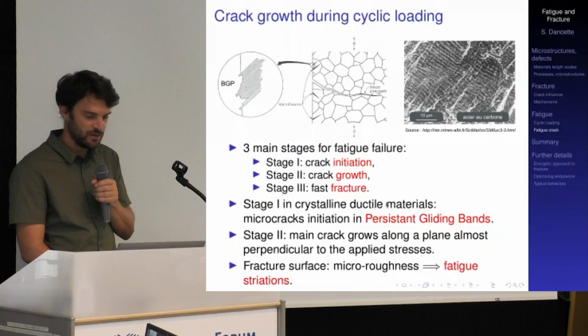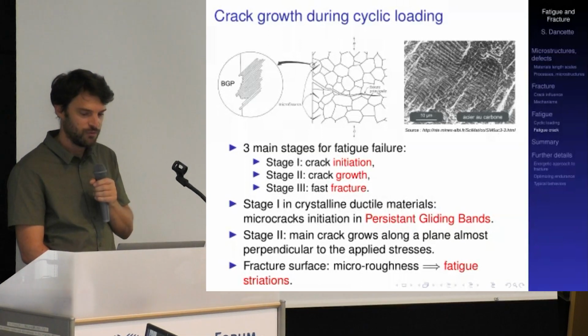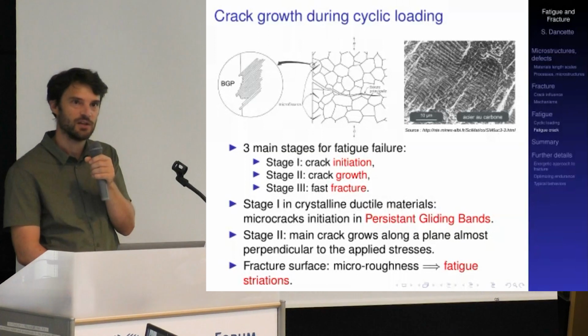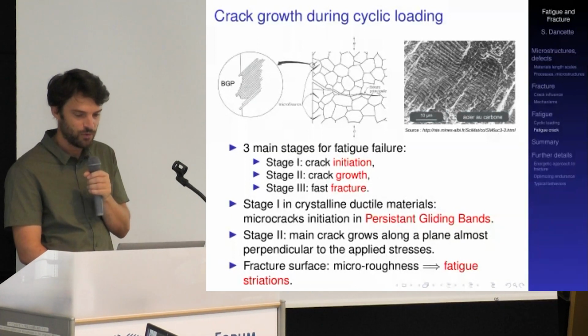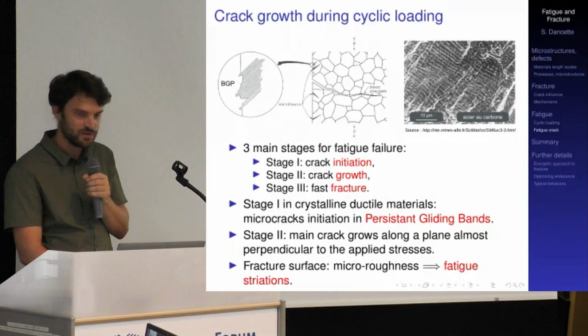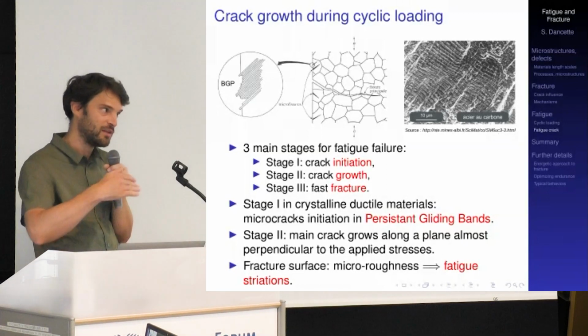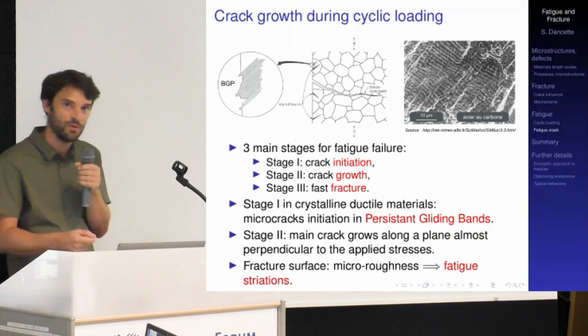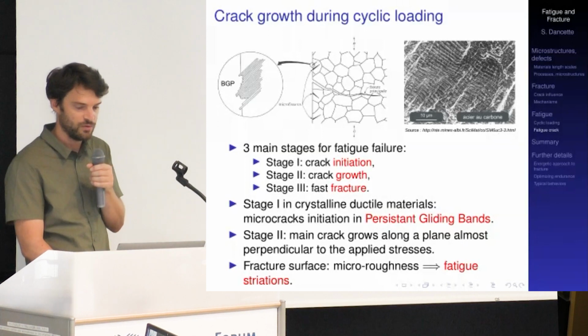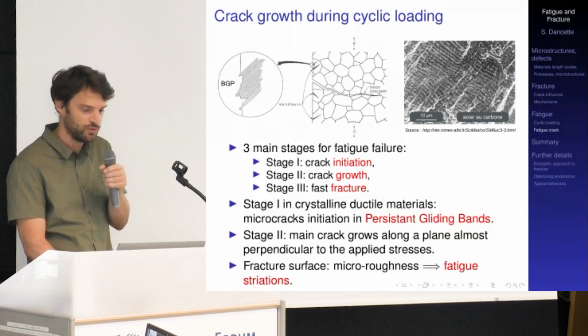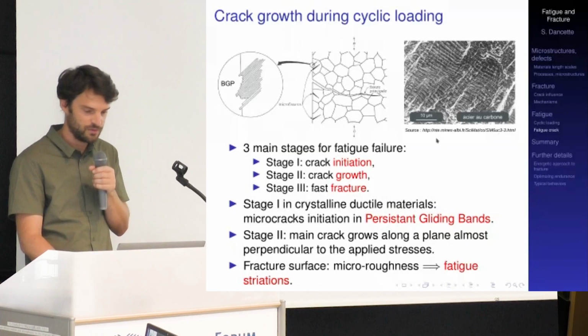So one interesting fact here is that when we look at the crack propagation, especially in the second stage, crack growth, if we look at the fracture surface with a scanning electron microscope, it is quite easy, for example, to distinguish these fatigue striations. So each of these striations here is a marker of the crack advance during crack propagation at each cycle of loading. And it can take place at length scales in the order of a few microns in the microstructure, so inside of the grains of the materials.